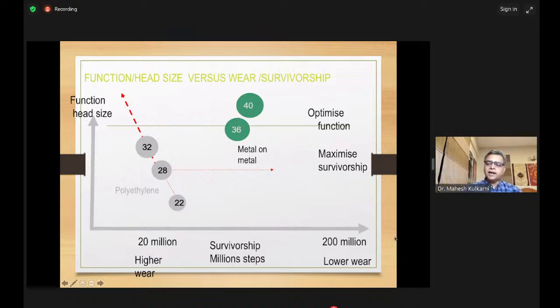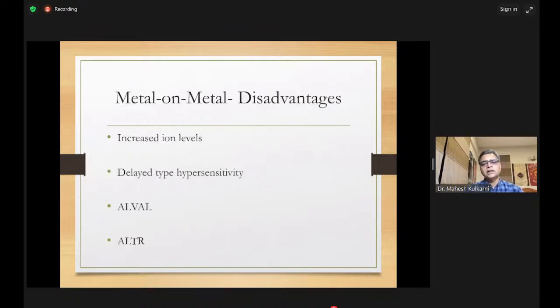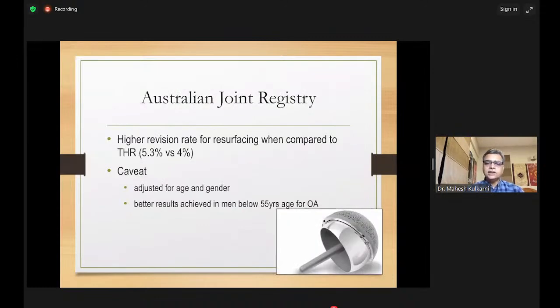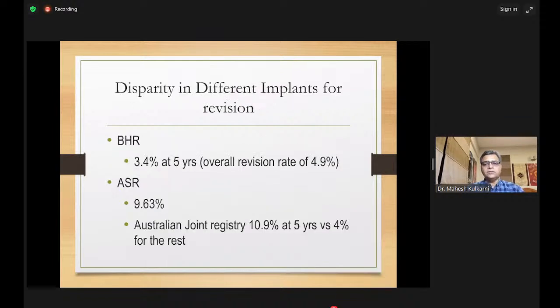But unfortunately, the metal on metal ion issue really was a bad one. The decreased tolerances with some of the companies which manufactured their implants led to massive problems of metal ion release, delayed type hypersensitivity reactions, ALVAL, that is the aseptic lymphocytic vasculitis-associated lesion, pseudotumors and failures. And if you see the Australian joint registry, there was a higher revision rate for resurfacing when compared to a standard total hip. A caveat was this was not adjusted for age and gender, and in men or below 55 years of age, the resurfacing hip replacement actually did very well.